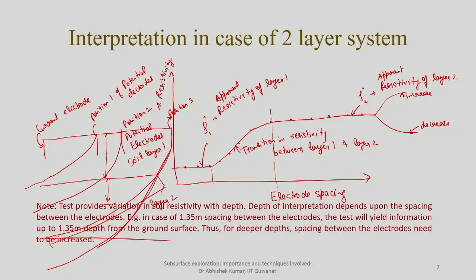One important note to be mentioned here is that the test provides variation in soil resistivity with respect to depth. The depth of interpretation depends upon the spacing between the electrodes. So, keep on increasing the spacing, and your equipotential line will show you the overall resistance offered by the material, even from a large volume of material. To give you an example, if the spacing between the electrodes is 1.35 meter, your test will yield information up to 1.35 meter depth with respect to the ground surface.